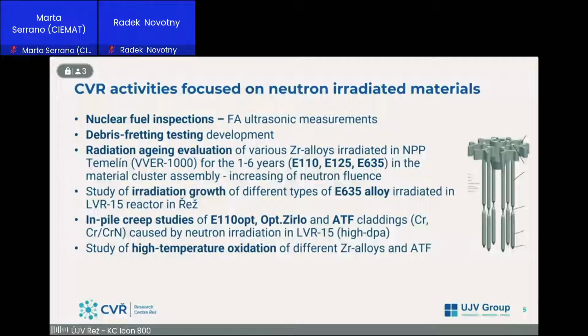Something about our activities, which are focused mainly on neutron irradiated materials. As I mentioned, we have the nuclear fuel inspection group, which is a huge support of the Czech nuclear power plants. We have a huge area of perspective methods, debris fretting testing. We have a lot of projects concerning radiation-induced damage evaluation of different kinds of zirconium alloys. There is the project of irradiation in the Temelín nuclear power plant from 1 to 6 years, and then we do mechanical testing and microstructure analysis depending on neutron fluence. So we evaluate the effect of neutron fluence on the microstructure.